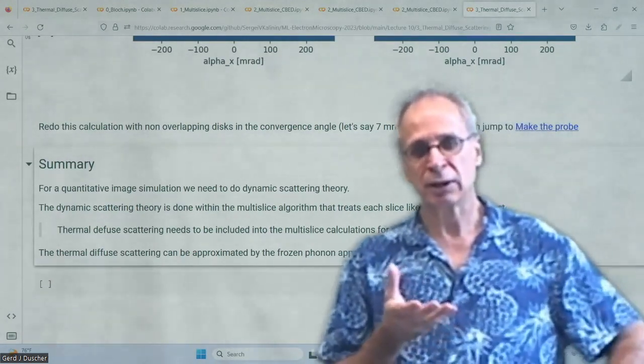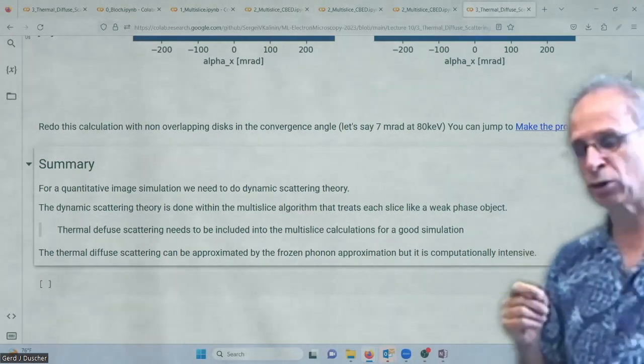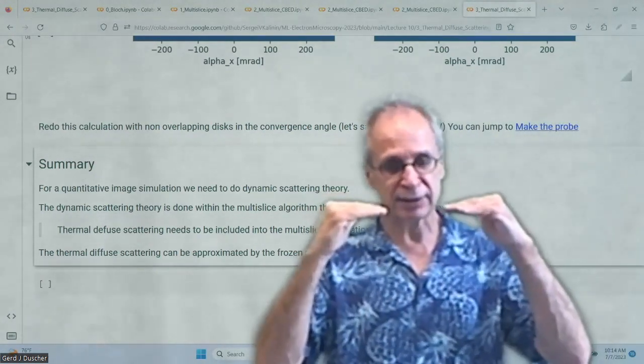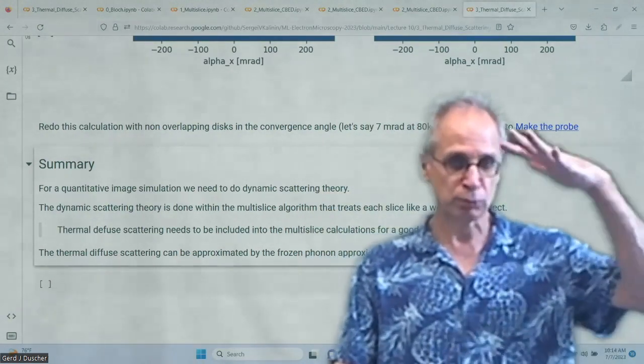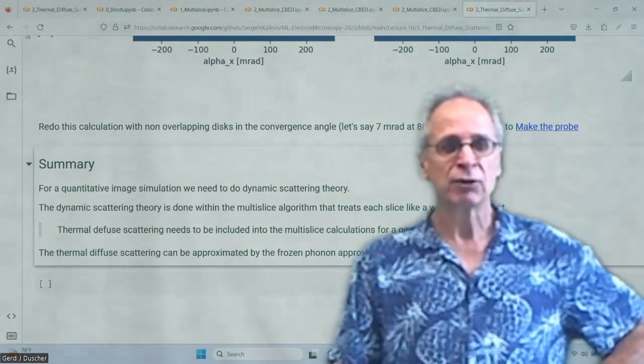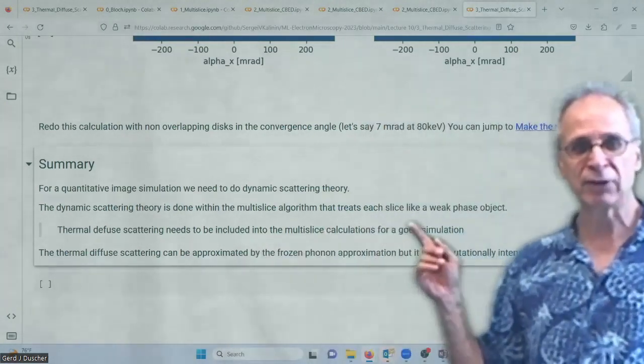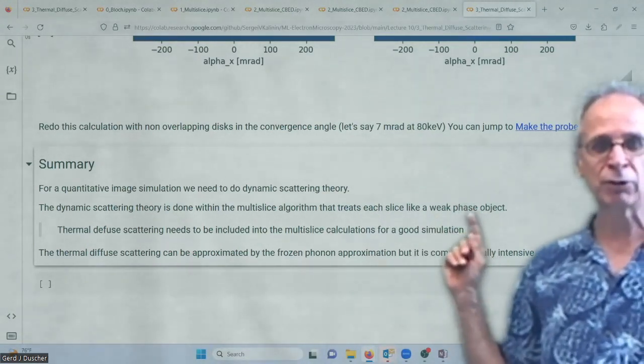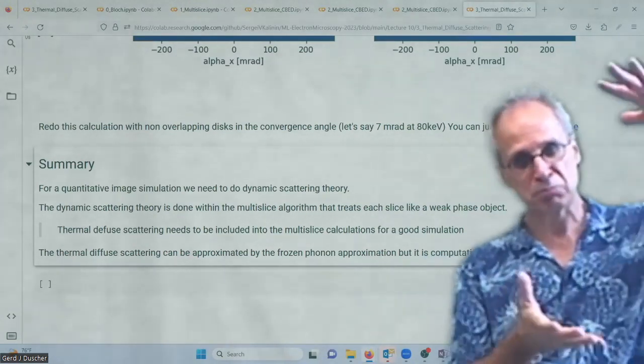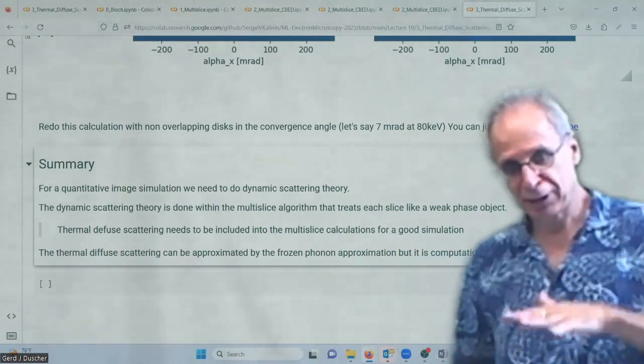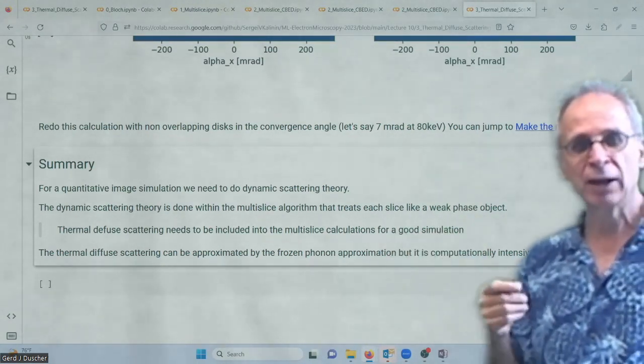The key ingredient for the Cowley-Moodie equation is that we treat each slice like a weak phase object — the only thing that changes within the slice is the phase of the incoming probe or wave. That is of course valid only since it is extremely thin. You cannot make the slice too thick or the weak phase object approximation will no longer hold. That gives you a limitation of how thick your slice can be within the crystal — you cannot just say 50 nanometers of strontium titanate and that's it. The weak phase object approximation would fail if your slice is very thick.